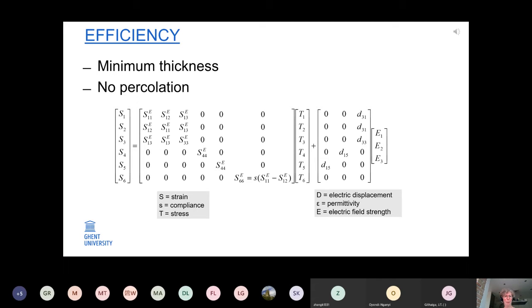Now, when you deform a material, the piezoelectric effect is a surface effect. So the energy you need for deforming the inside, the bulk of the material, is actually wasted. Part of it will be recycled, but as you know, deformation for most materials is not fully elastic. It has some hysteresis, and this is a loss of energy. For a thick material, of course, this energy loss will be higher, whereas the piezoelectric effect is purely surface. So the bulk material doesn't add any additional power.